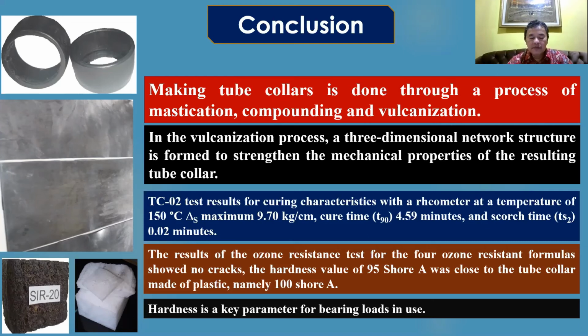The result of the ozone resistance test for the formulas showed no crack. The hardness value of 95 Shore was close to the tube collar made of plastic, namely 100 Shore. Hardness is a key parameter for bearing loads in use.